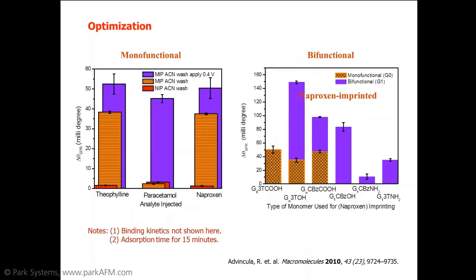Okay. So we did some optimization studies. Looking at this graph, the monofunctional monomer was washed with acetonitrile. And we found that by washing it with acetonitrile and at the same time applying a constant potential of 0.4 volts, actually produce the biggest response on the SPR curve. Also, we compared between a bifunctional and a monofunctional monomer. In general, the bifunctional monomer is a superior design compared to the monofunctional units.